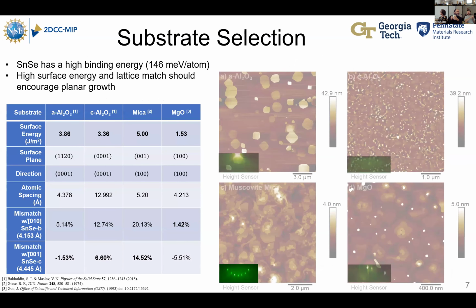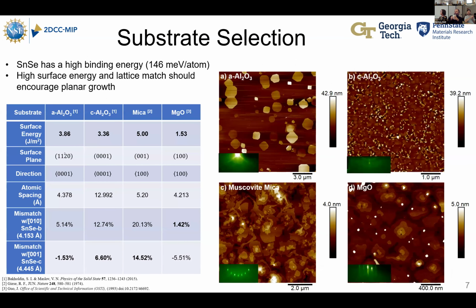All right, other questions for Jonathan? It's just curious that the magnesium oxide was the best substrate. If you go back to the first table, the lattice mismatch and the surface energy were, maybe the surface energy was low. So the mismatch is low.